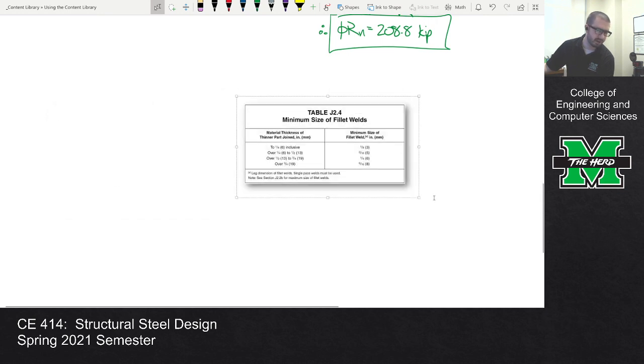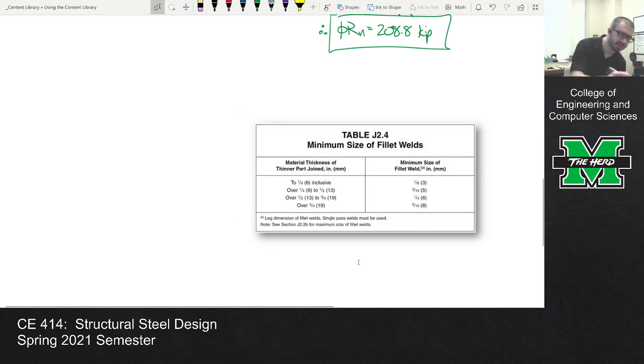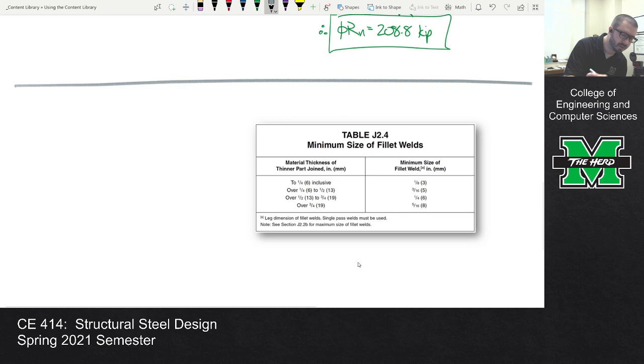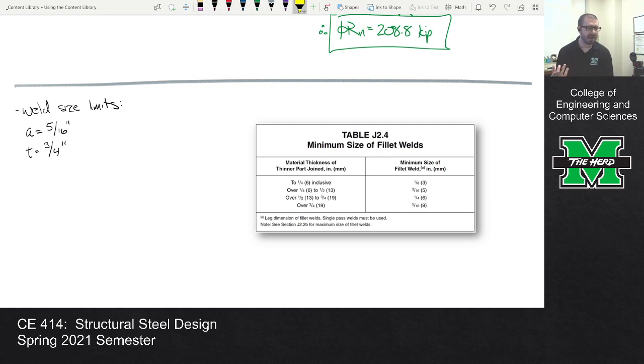Okay. So we're also going to check our weld size. Remember, we had a weld size that was 5/16, and then we have a thickness that's 3/4. The plate in this instance was 3/4 of an inch, okay? And for a plate that's over 1/2 inch to 3/4 of an inch, the minimum weld size is 1/4 of an inch. So a minimum is 1/4 of an inch.